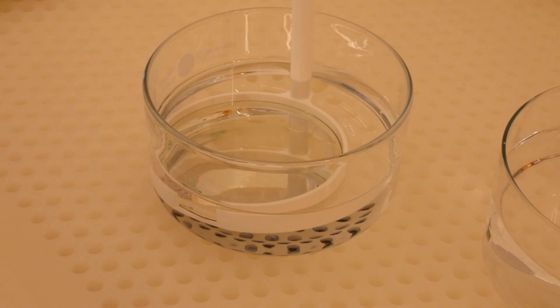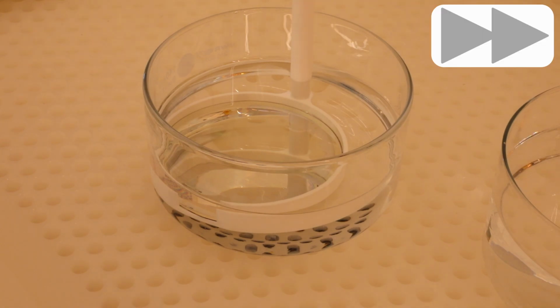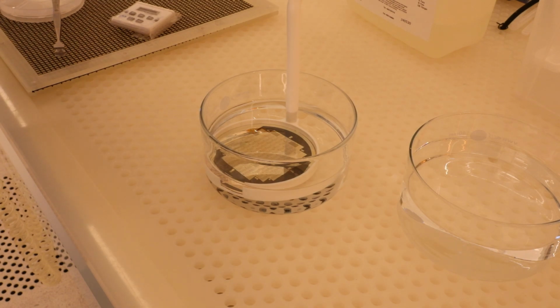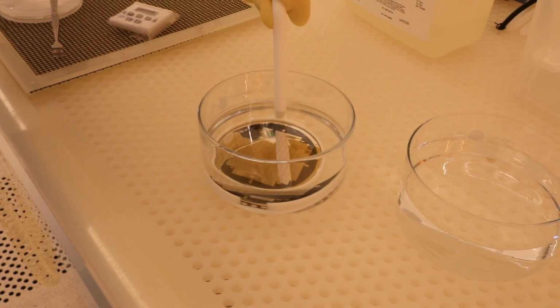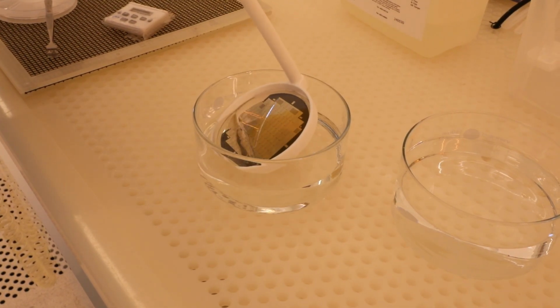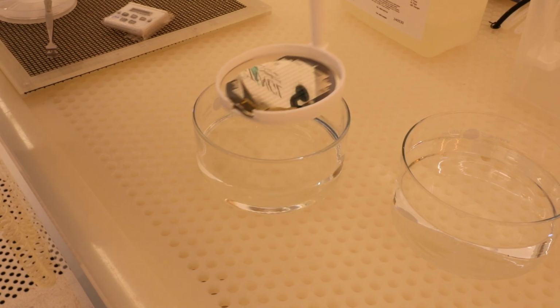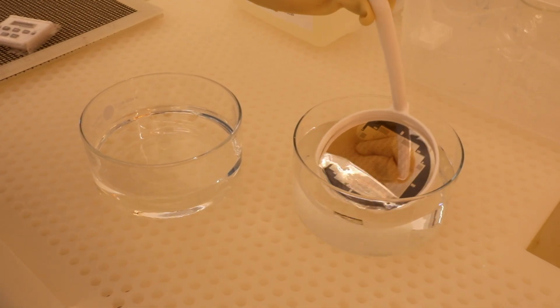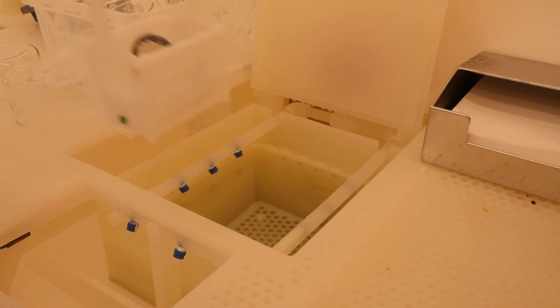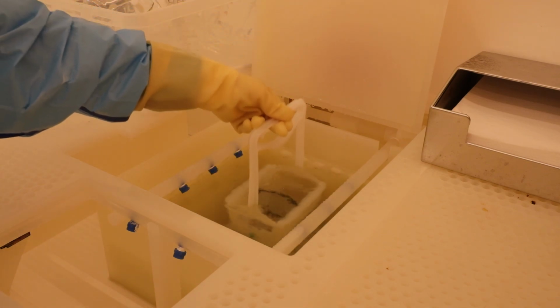Now we can see some black areas appearing on the wafer, starting from the edges. That is the underlying silicon substrate peeking through, in the spots where there was a gap in the pattern resist and the unprotected aluminum was allowed to have direct contact with the etchant solution. After the full pattern has been etched into the metallic layer, we can stop the chemical reaction in a beaker of water. And more water.